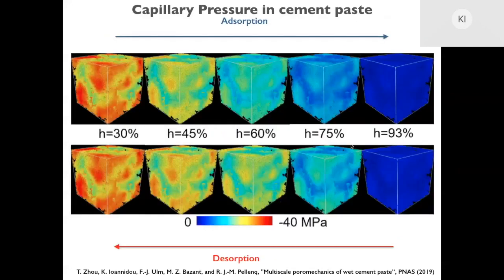So for example, here you can see how the capillary pressure is distributed in our sample. With the color code we are able to go to regions that are 100 or 200 nanometers, and we can forget about the grains that are only 5 nanometers. And what you've seen here is that, of course, at the lower relative humidities is where we have the highest capillary pressure, and this is mostly localized in the densest part of the solid, where we have a lot of small pores. Whereas the blue path that you see around is basically the large capillary pores, where the capillary pressure can be released, so it's not so high.